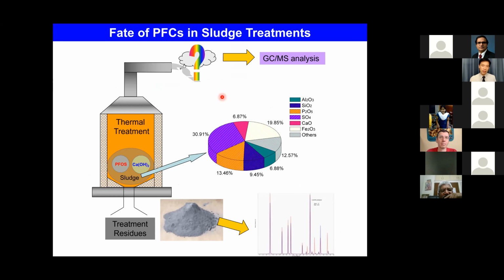So we say, okay, then let's try to see whether under this temperature, or before this temperature, any reaction can already be triggered, and therefore even at higher temperature, the perfluorocarbons are still not going to be a problem. And what we will be looking at is the ash generated from that. Because from the ash generated, we can do X-ray diffraction, we can do quantitative X-ray diffraction analysis, and we will really see where the fluorine is. Is the fluorine really being released to the air as fluorocarbons or not?